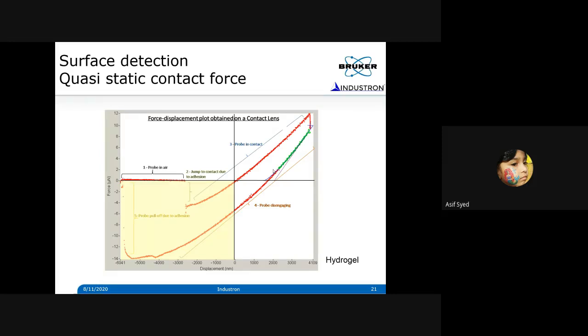And with the standard commercial nanoindenters, you buy them, they spit out this load displacement curve, and then you jump in and use the standard protocol and measure the properties. You're totally wrong. Okay, and that's what I wanted to point out. You have to measure the whole curve, okay, including the adhesive and the repulsive interaction.